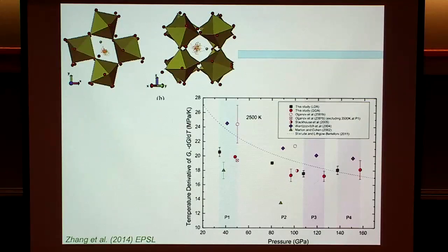This is magnesium silicate perovskite, we did some molecular dynamics simulations of this material. And what's represented here are the SiO6 octahedra that make up this structure, and in the middle, the magnesium sitting in this big site. And this golden knot here is the path that the magnesium atom takes during the course of this simulation. Very large amplitude, very complicated, quite anharmonic.